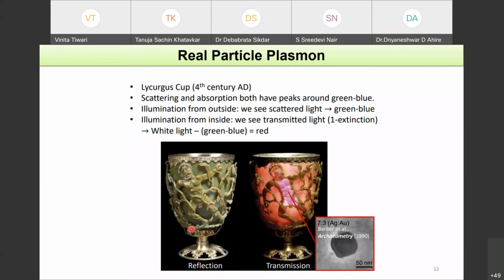So the reason is, when you see the reflection, this is basically the scattering resonance of the nanoparticles which are embedded in the glass, and they resonate at blue green. So you see it like this, and when the light source is inside, blue green is getting absorbed. So white light minus blue green is red, and that is why you see red. It means their absorption cross-section or absorption resonance is also at blue green. So this is where your nanoparticles can actually give you some very interesting phenomena.